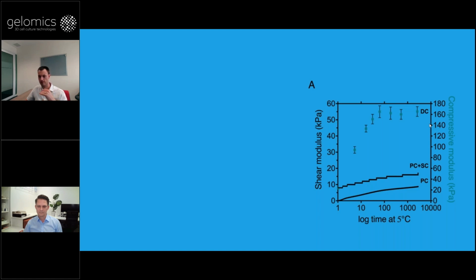and you can see how it is really a synergy. So it's not just adding the two effects together, but they actually work synergistically to get a much higher stiffness. And it's about 1 hour in the fridge that is about the time where this starts plateauing. So that's probably a good time then. That's what we took forward with the cells as well. And most cell types are quite happy for an hour in the fridge.